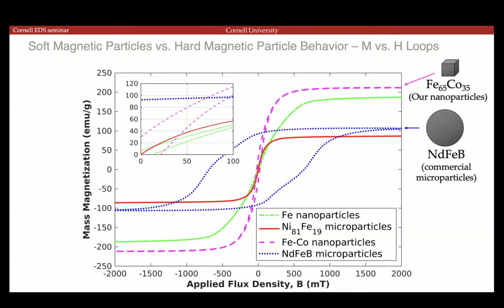So the domain flipping operation needs to be low dissipative. Yes, low energy dissipation. So I think your goal is actually the same as ours. In our case, the iron cobalt, as long as it is a single domain, so there are no domain walls, you don't have to deal with the pinning. It'll still have a very steep curve, but right now it's not straight, and we want to make it so. The iron cobalt thing looks really good.